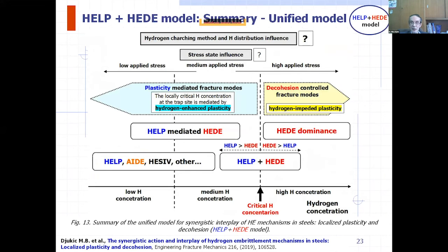steel constructions, and in this case, boiler tubes or pipelines, typically we have a hardening of material due to hydrogen, which is related to the decrease of plasticity phenomena, as shown here on our diagram. I will show you. As you can see, we have hydrogen-impeded plasticity, which means hardening of material upon reaching a higher concentration at high applied stress.